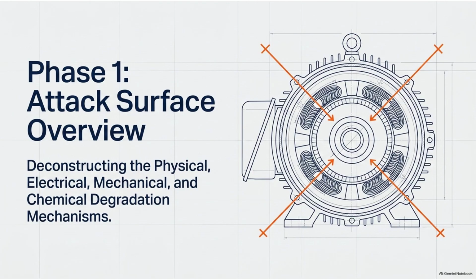Exactly. But when a voltage wave moves that incredibly fast down the cable from the inverter to the motor, it encounters the parasitic inductance of the stator coils. Because the wave is so steep, it doesn't distribute evenly across all the windings. It slams into the first few turns of the wire like a wave hitting a breakwater. Wow, okay. You get a transmission line reflection effect, which can actually double the voltage right at the terminals. So the very first loop of copper wire takes a massive, disproportionate voltage strike. Yes. And when that localized transient voltage exceeds the ionization threshold of the microscopic air gaps trapped between the wires, it triggers a partial discharge.